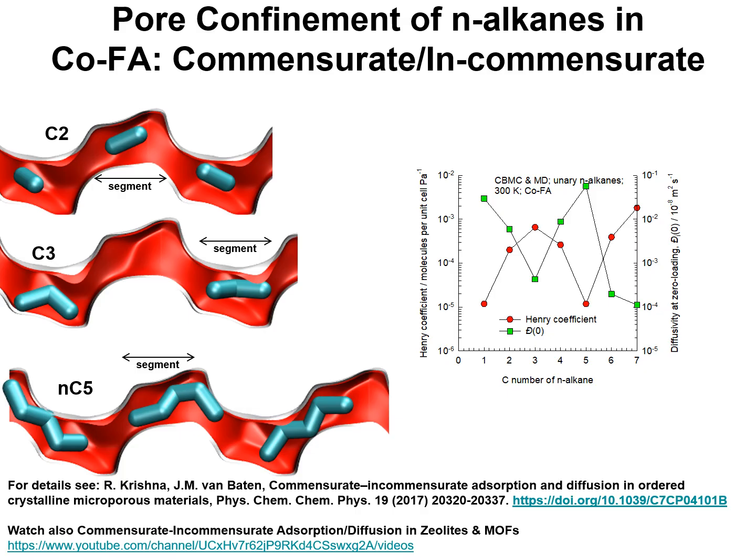Let's examine the diffusivities of normal alkanes in cobalt formate that consists of zigzag channels that are one-dimensional. This is the length of one segment. This is the second segment. A propane molecule has a length that is commensurate with the segment length, and it sits comfortably.